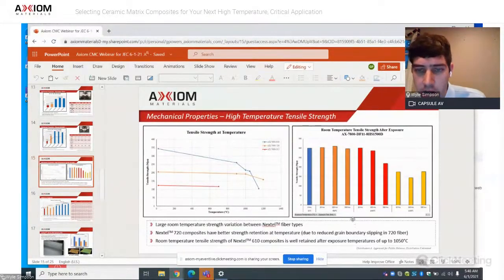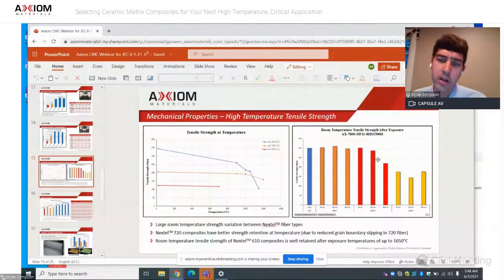You can see here 900 degrees Celsius. The mechanical properties stay pretty consistent over a 500-hour cycle at that temperature. Then when you get to around 1,100 degrees Celsius, for long periods of time, that 610 fiber starts to creep, and those tensile properties start to lessen after long periods of time.